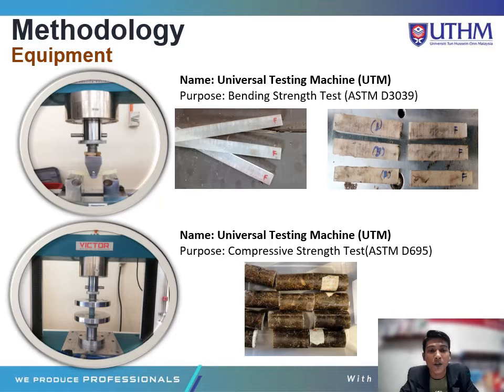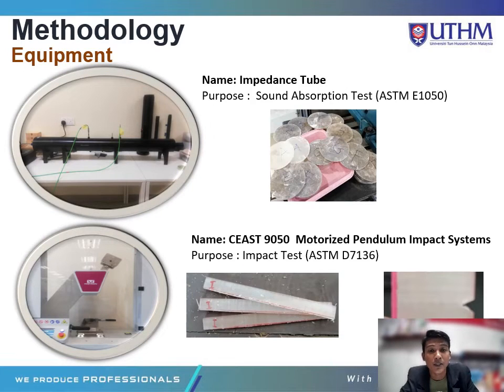And for the compressive strength test, I'm also using the UTM, universal testing machine, with the standard code ASTM D695. For the sound absorption test, I'm using an impedance tube. And for the impact test, I'm using the CEAST 9050 motorized pendulum impact system, and I'm using the standard ASTM D7136.